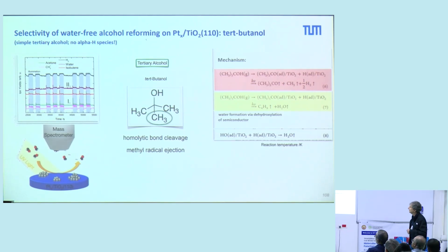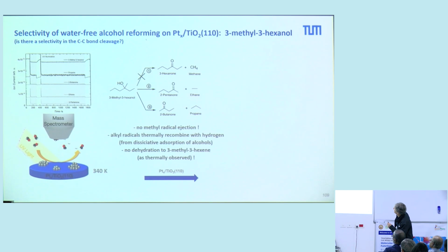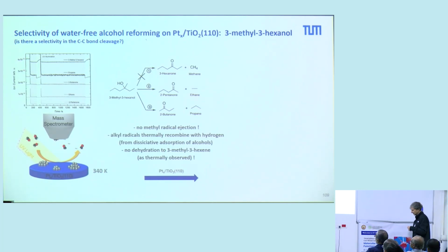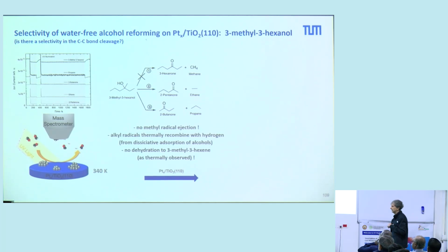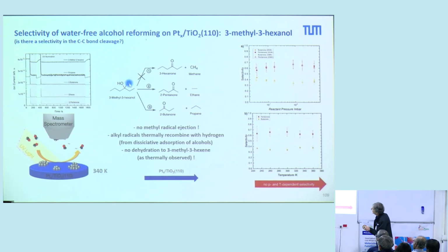Other tertiary alcohols, here 3-methyl-3-hexanol. Here we now have different hydrocarbon chains. And the question is whether we have a selectivity. What you observe is that in this case, we didn't see any methane or CH3 radicals, but we make the splitting in the other position here or here. And we are producing pentanone and butanone. Again, with a very defined selectivity. It is independent of the pressure, it is independent of the temperature, it is simply related to this photostimulation, the oxidation of the reaction with the hole of this methoxy species, and we produce this with a very defined reactivity.